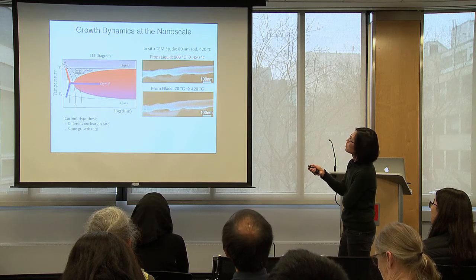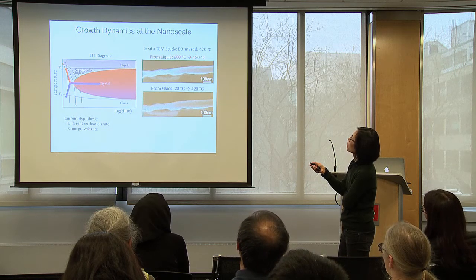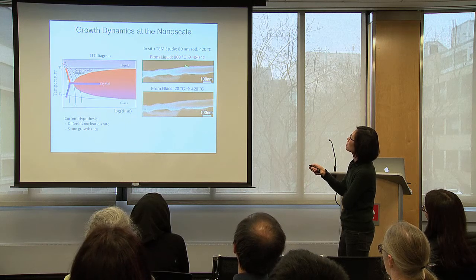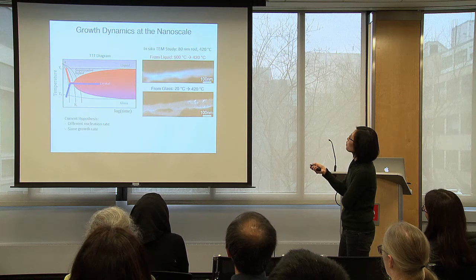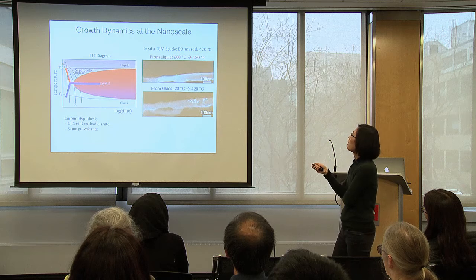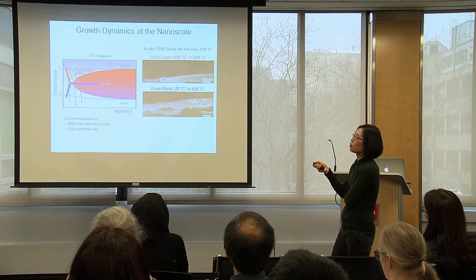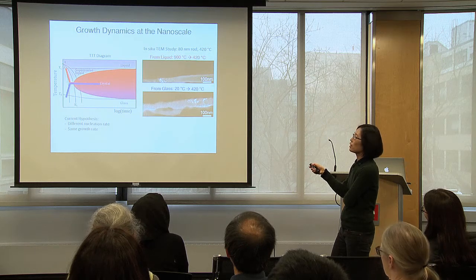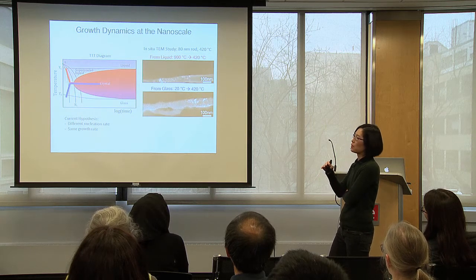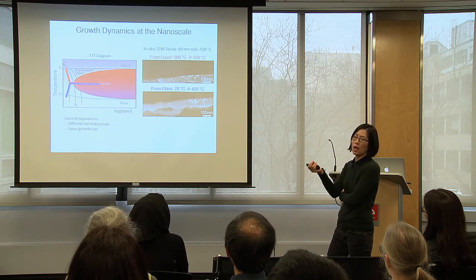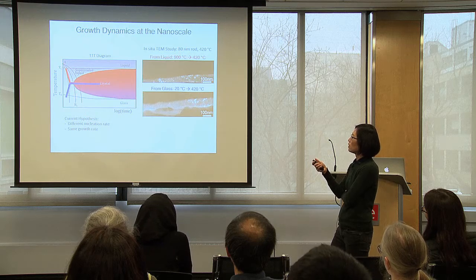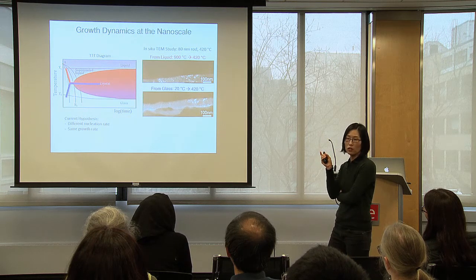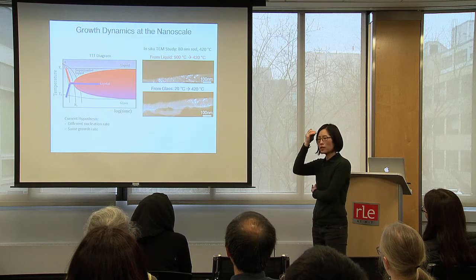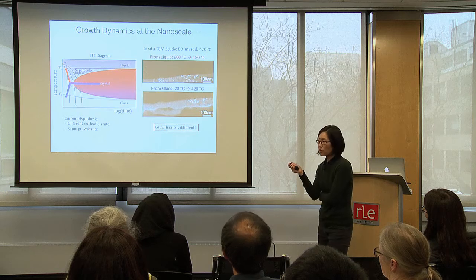So this is the same rod. We just recycle our rod. We're doing isothermal growth at 420 degrees Celsius. The first one is coming down from the liquid side. The other is from the glass side. Okay. And what we observe is that the growth rate coming from the glass side is much faster. And this is coming from the liquid side. I don't know if you notice, when we go from 900 to 420 degrees directly, there's a jump, because you're changing the temperature drastically. I think it has to do with the way the chip is designed, so some companies bypass this. So the growth rate is different, okay?